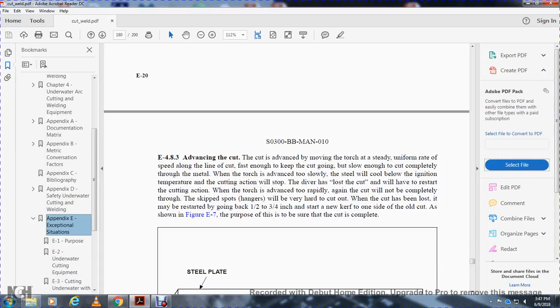E-4.8.3 Advancing the cut. The cutting is advanced by moving the torch steady, at a uniform rate of speed along the line of cut, fast enough to keep the cutting going, but slow enough to cut completely through the metal. When the torch is advanced too slowly, the steel will cool below the ignition temperature of the cutting and the action will stop. The diver has lost the cut. Once lost, the cut will have to be restarted.